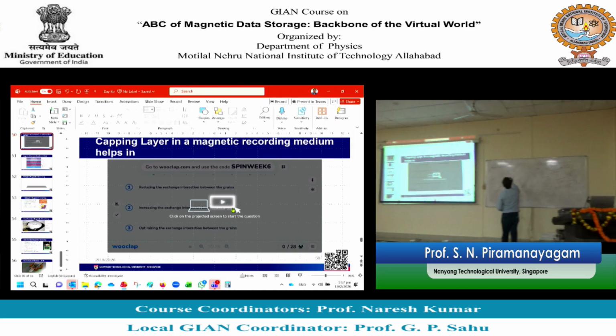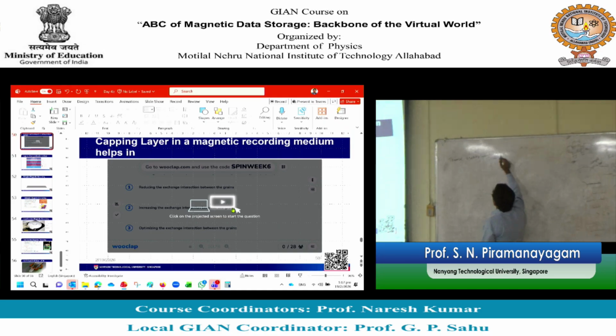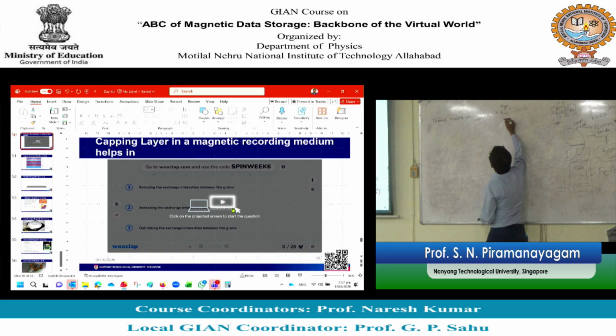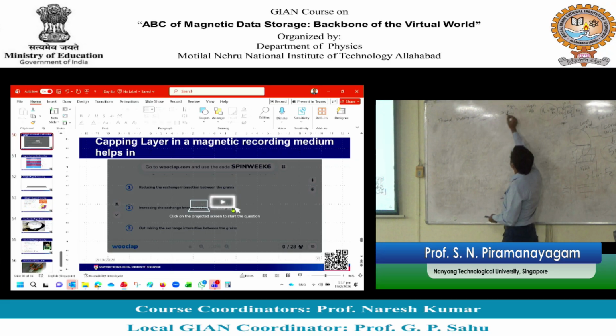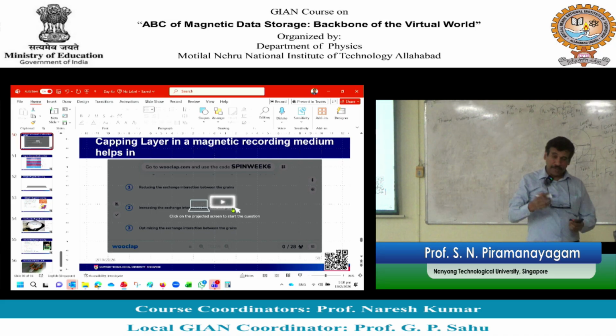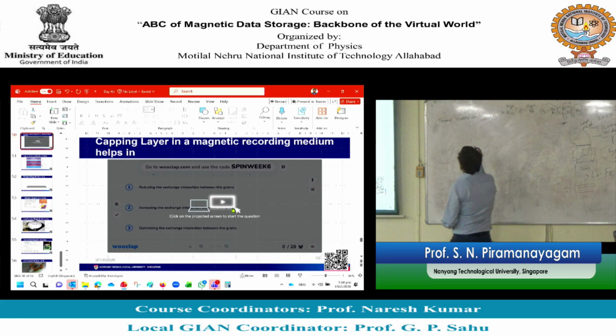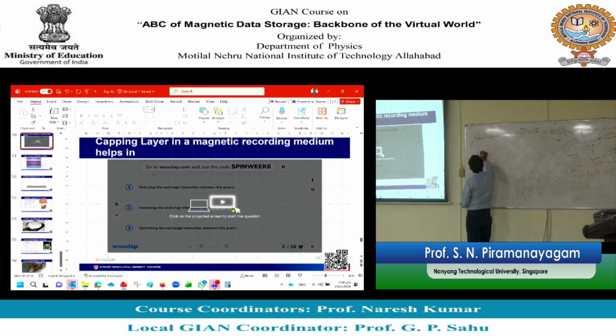The only material that is usable for future recording is iron platinum, because we need high anisotropy to make the bits smaller, and we need a high Ms so that your HK is not too large. HK is 2 Ku over Ms, right? So if Ms is small, then your HK is going to be large. So again, useless. The only material that can meet future requirement is iron platinum with this high anisotropy and high saturation magnetization. With iron platinum, you can make even 4 nanometer grains or 4 nanometer dots.